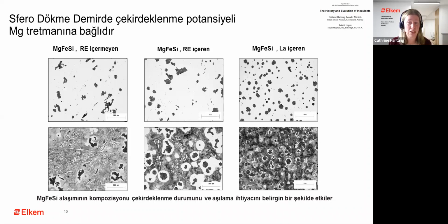This is because the magnesium treatment alone cannot provide sufficient suitable nucleation sites. But there is a difference in what kind of nucleation sites you can generate or could potentially generate from a magnesium treatment. And in this slide, we can see an example of how different the nucleation conditions can be with different magnesium ferrosilicon qualities. So here we see the structure in polished and etched condition of samples that we have collected from trials in our lab using different magnesium ferrosilicons.